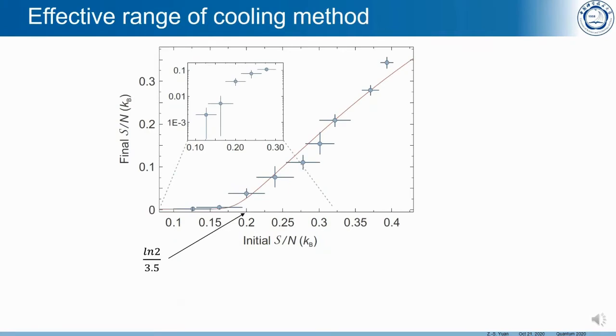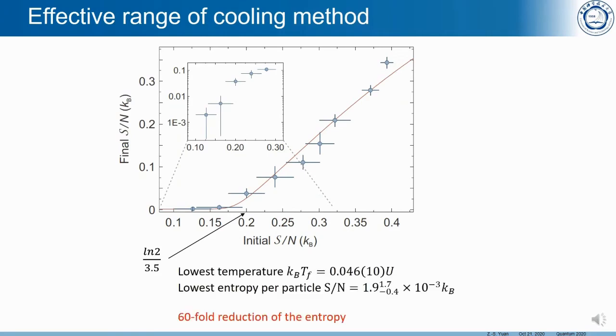This curve shows the entropy per particle before and after the cooling. We can see that when the initial entropy is higher than 0.2, the cooling effect is limited, and the reduction of the entropy is by 1 to 3 times. However, when the initial entropy is lower than 0.2, the reduction of the entropy is dramatic. We finally found a 60-fold reduction of the entropy due to the cooling.